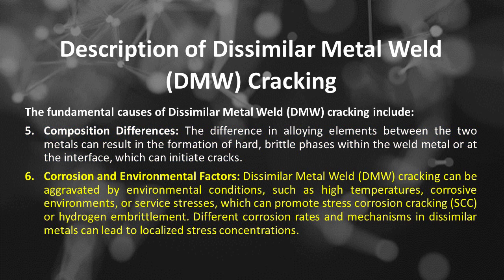Number 6 is corrosion and environmental factors. Dissimilar metal weld, or DMW, cracking can be aggravated by environmental conditions, such as high temperatures, corrosive environments, or service stresses, which can promote stress corrosion cracking, or SCC, or hydrogen embrittlement. Different corrosion rates and mechanisms in dissimilar metals can lead to localized stress concentrations.